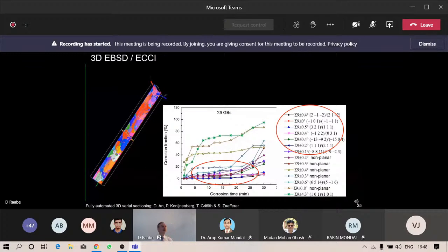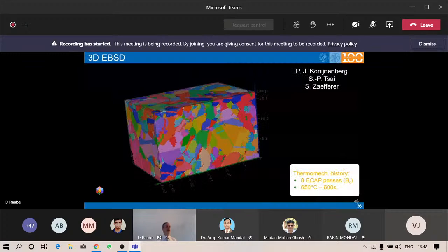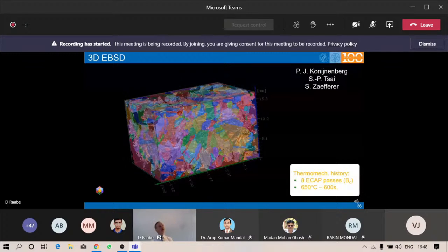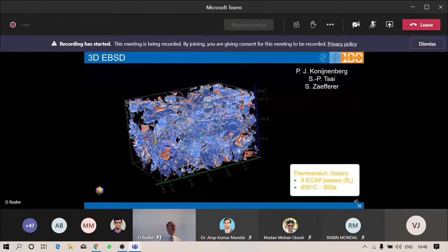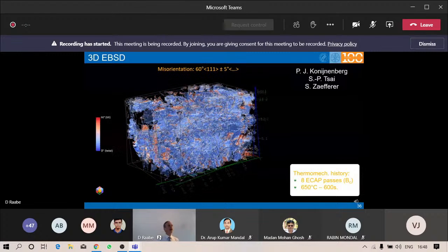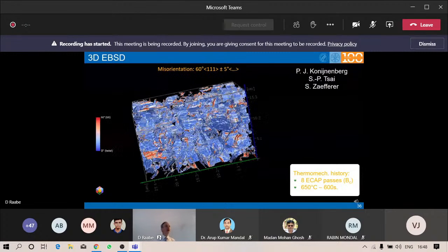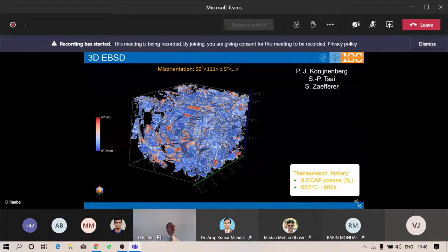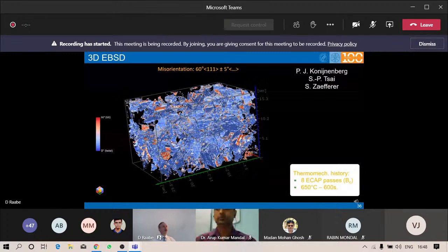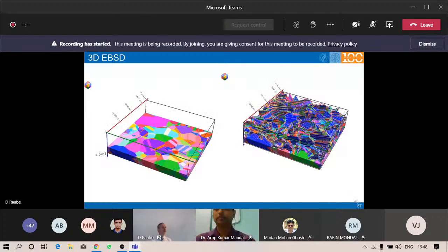Or you get results like shown here from a copper sample that was subjected to an ECAP process. There was a project by Peter Konijnenberg and S.-P. Tsai and Stefan Zaefferer, where you get not only the three-dimensional microstructure, but of course all the associated higher order kinematic information, such as the nature of the crystallography of the grain boundaries, like showing here the population of the 60° 111 grain boundaries. You can differentiate between the tilt and twist boundaries. And you get data packages such as shown here, where you see both the grains. You also get, of course, the individual pattern qualities and so on for discrimination among phases and the associated interfaces.